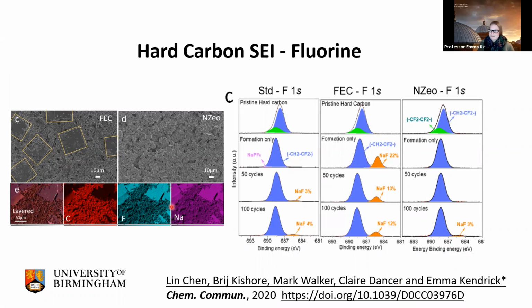So going back to what was quite a lot of work initially to try and promote high power electrodes for sodium ion, we actually found that the zeolite additive did not do what we thought, but actually stabilized the SEI layer instead. And we proved this by adding it to the electrolyte also.